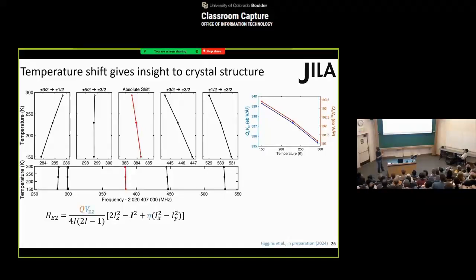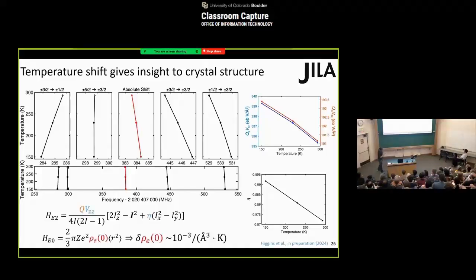So this actually gives us a very good measure of the local electric field gradient change with respect to temperature. And also, this eta parameter, which indicates the asymmetry of the field gradient, also changes with respect to temperature. And that's essentially corresponding to an anisotropic thermal expansion of the crystal along different crystal axes. So we can also extract some estimates about the local charge density, based on local electron charge density at the nucleus through this monopole interaction, and how that changes with respect to temperature.